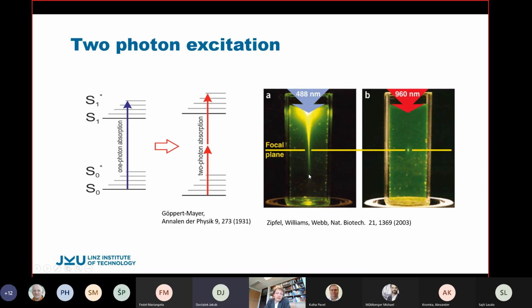Now Goeppert-Mayer introduced theoretically in 1931 two-photon absorption. When you use the same cuvette and you put in near-infrared light, then you see that only in the focal plane you excite the fluorophores, and that is used by two-photon microscopy to give you this nice effect that you really have a sharp view just from the focal plane.